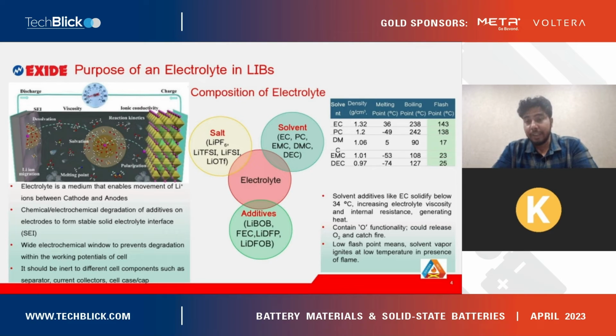These slides talk about why we need electrolytes. It's about helping the movement of lithium ion from one side to another, and there is a lot of electrochemistry and chemical reactions involved in these steps: the hopping mechanism, solvation, desolvation, the donor numbers, and the addition of SEI layer to have a stable interface. And you need SEI because you don't want your electrode material to get exposed to the electrolyte, so that electrolyte degradation and irreversible coulombic efficiency loss happen. So those are the reasons why you need a salt, a solvent, and additives particularly.